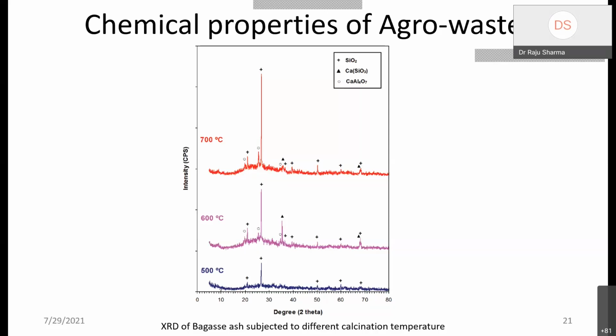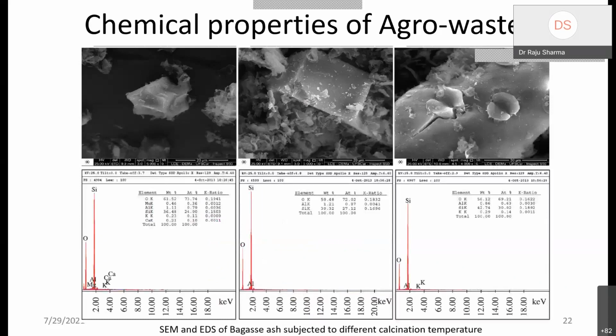If you use 500, it may act as a filler, but if you use 700, it may react and give reactivity with the other products and increase the performance of the concrete on a macro level and on a microstructure level. Now, if you go with the morphological analysis, you can see that here they found this kind of crystal, right?